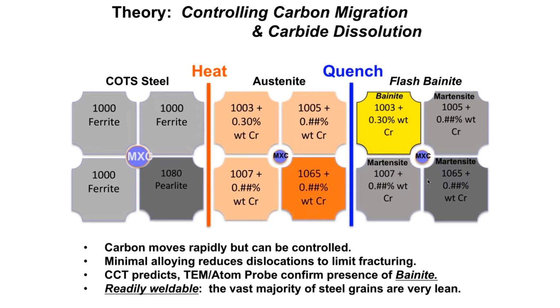Now, we have worked with Professor Suresh Babu at various institutions that he's been with, and through TEM and atom probe ion field microscopy, we've actually verified the presence of bainite in our microstructure, even though we've quenched in water, which is kind of unexpected, I guess you could say. The other thing that's happened is we've taken this chemistry, run it through Edison Welding Institute's CCT calculator, and it in fact does predict that this chemistry, when cooled very, very rapidly, can make bainite.